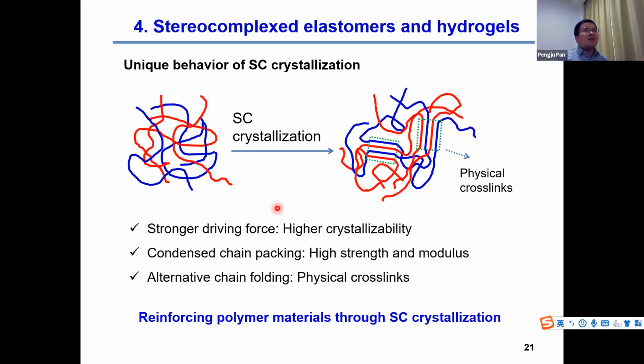Some non-crystallizable polymers can become crystallizable through stereocomplex crystallization. Second, because the polymer chains pack more densely in the stereocomplex crystal, they will have higher crystal modulus and strength than the common homocrystal. Third, stereocomplex crystallization needs an alternating packing of two different polymer chains. The formed stereocomplex crystal can function as a physical cross-linker in the material. Therefore, stereocomplex crystallization would have a better reinforcing effect on the polymer material.